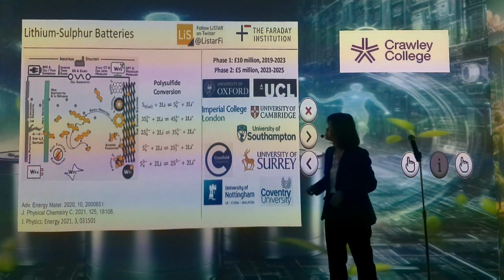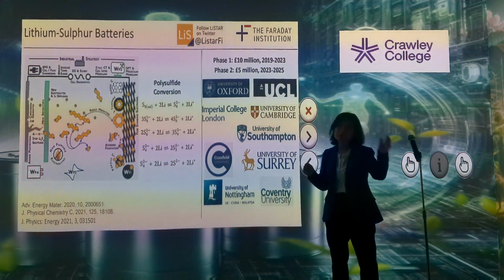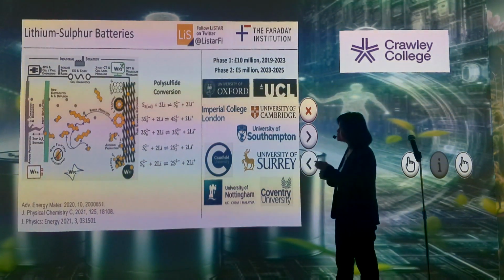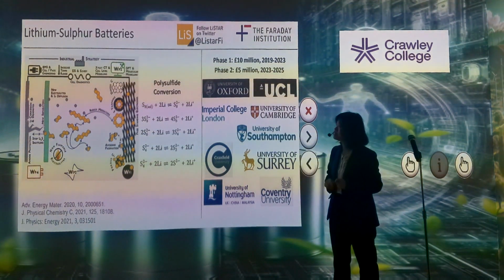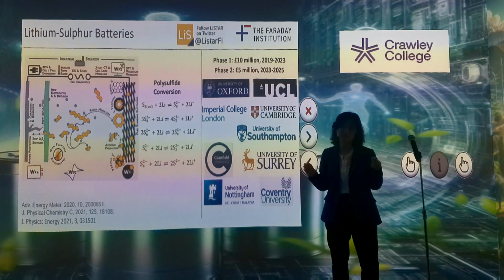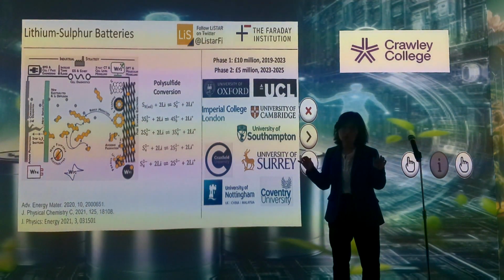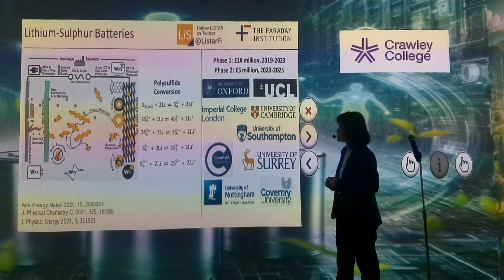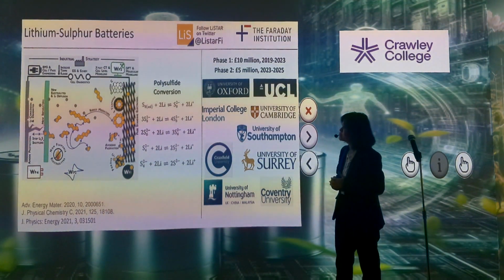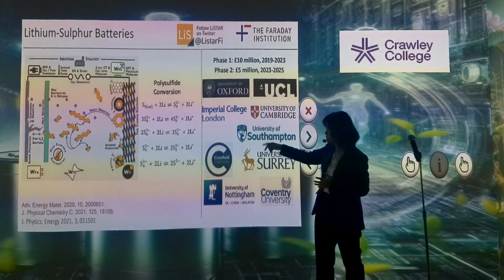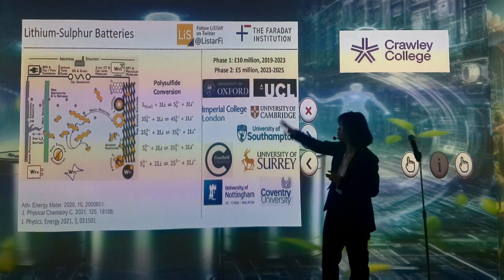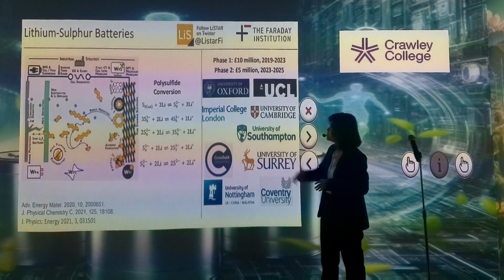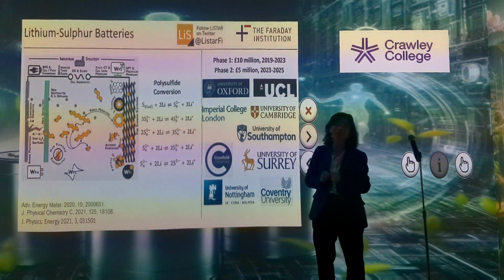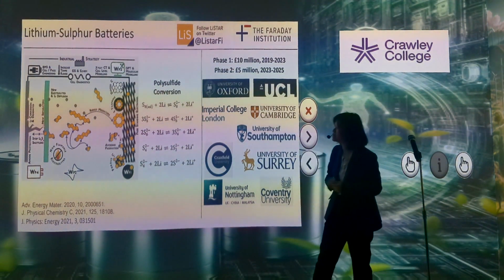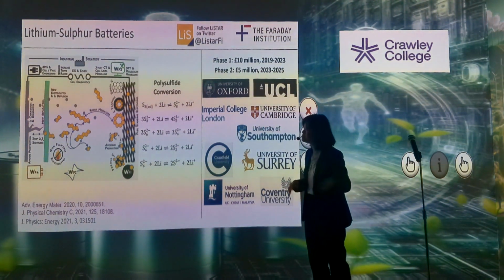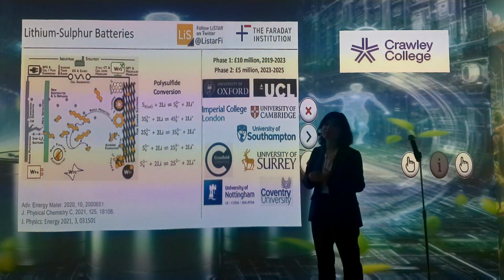Now I'm coming to another type of battery, still using lithium metal as anode, but the cathode now is completely different. The cathode material now is sulfur. And we all know sulfur is very cheap and very abundant and also light. So it does provide a lot of advantages for this type of battery. The challenge is, though, you have the conversion of the sulfur molecules. The sulfur molecule in the initial stage is S8. And it will go through a series of conversion reactions to create polysulfide molecules, and those polysulfide molecules are soluble in liquid electrolyte, so they dissolve in the liquid electrolyte and migrate to the anode and react with lithium metal, and so there's a very bad degradation happening there.